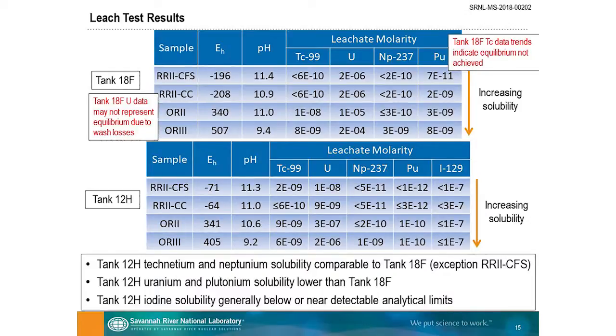So here are some results. There's a lot of numbers. I won't go through all of them. The things you want to notice is that the EH range that we achieved was about negative 200 to positive 500 for tank 18. That's the 0.7 volt range I referred to. pH targets we generally reached. Concentrations of the radionuclides on a molar basis in general are really low. E to the negative 10th, E to the negative 9th, or even 11th. Uranium was the most soluble radionuclide. These are concentrations even after losing most of the uranium to the wash. Uranium came out much more easily than the other radionuclides. We had some other issues. Technetium data trends for tank 18 indicated that even in 2 months we might not have reached equilibrium.